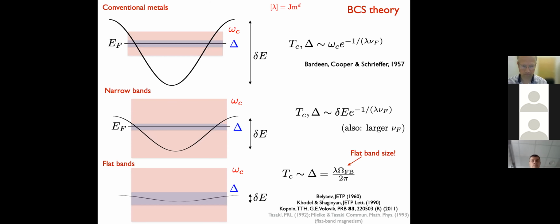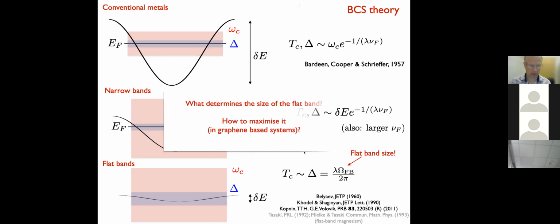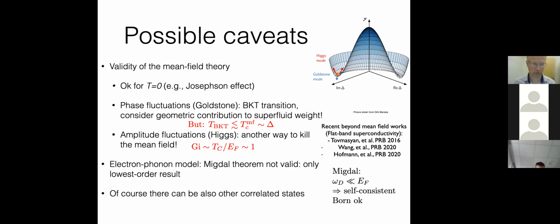So basically what you get is this linear scaling between delta and the interaction strength, but you also get this flat band size as a parameter of your model. And this is the aspect from which I want to approach the different flat bands in my talk today. So then the natural question is what determines the size of the flat band and how to maximize it in systems that you might be considering in experiments. In this case, I focus on graphene-based systems.